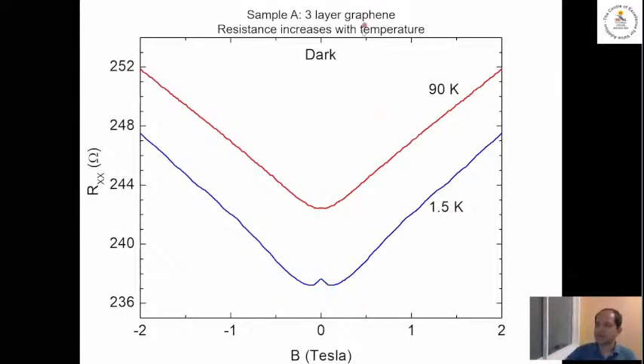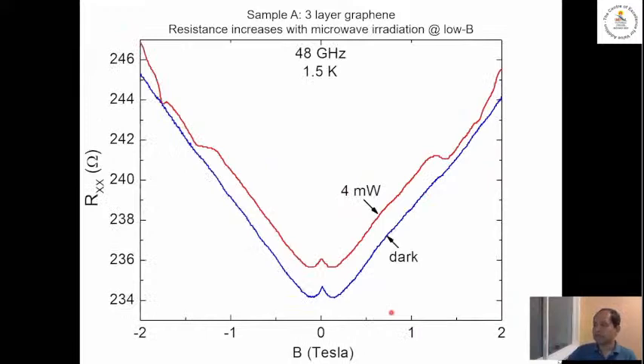So this is the 3-layer sample in the dark. Increasing temperature here means increasing the resistance. So what happens if you apply microwaves? Again, we have resistance versus magnetic field to 2 Tesla. The blue curve is the result in the dark. The red curve is with microwaves, 4 milliwatts at 48 gigahertz. What you see is that when you apply the microwaves at a fixed temperature, the resistance goes up.